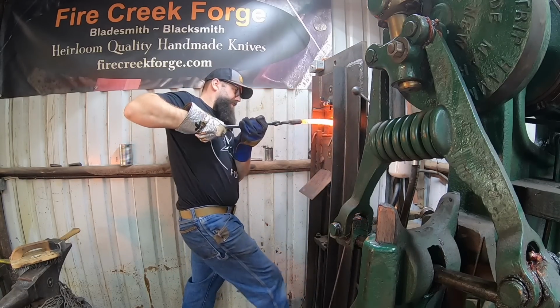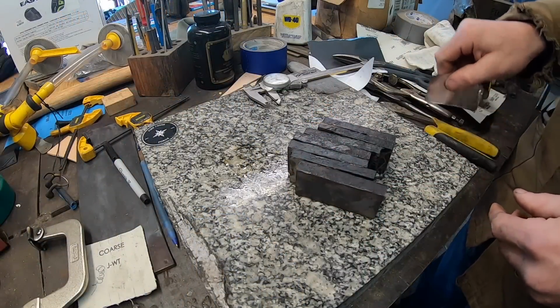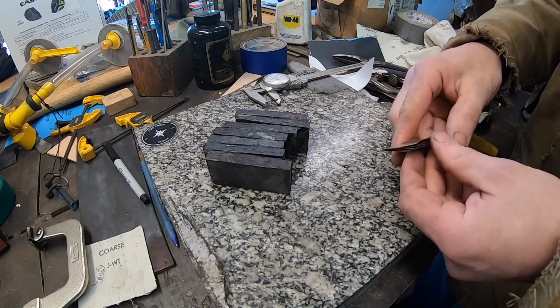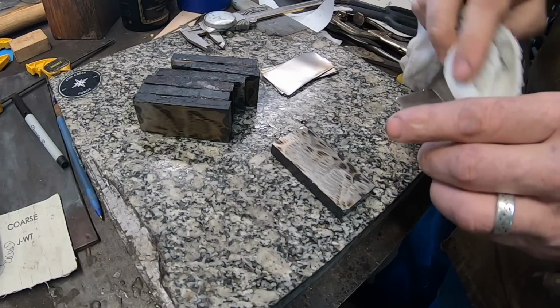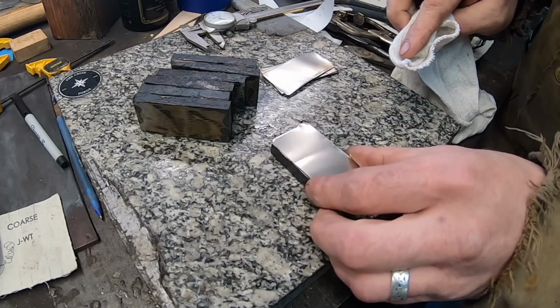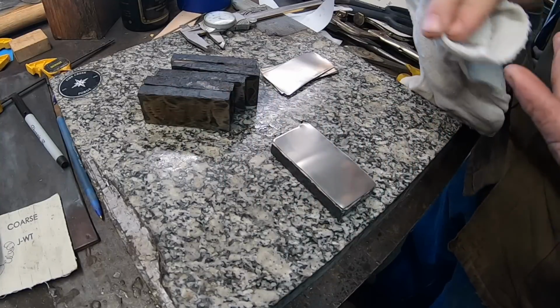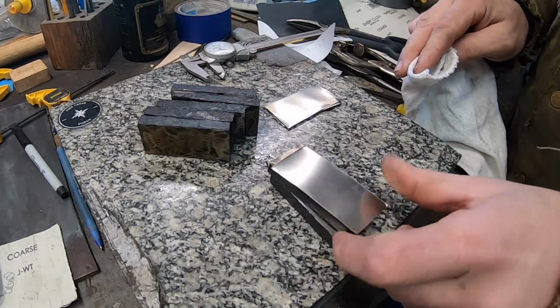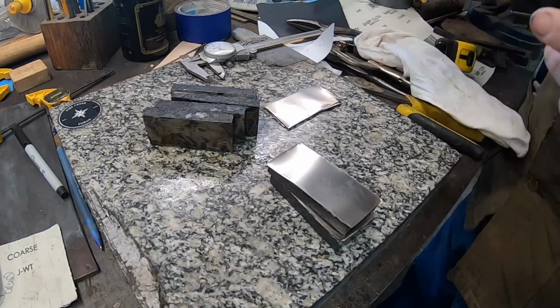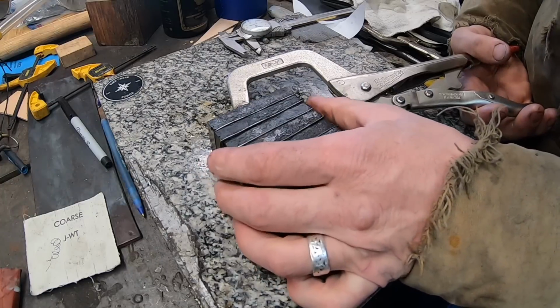And at this point we have a layer count, but I'm going to recut it and restack it and then add some additional layers of nickel in there, and that should put us up to around 170 layers between the 1045 and the nickel pieces.